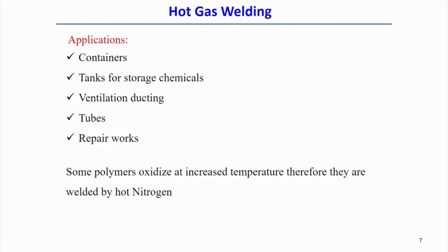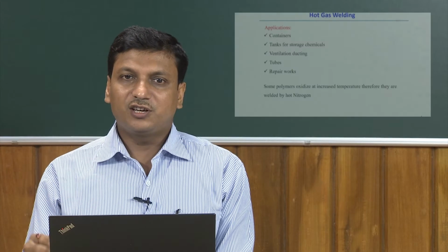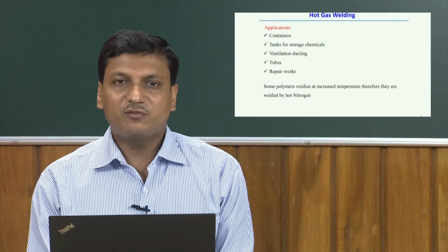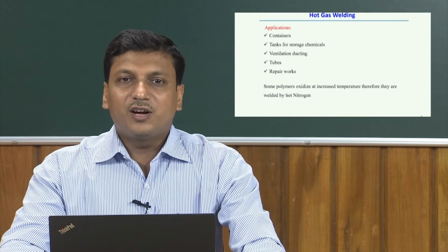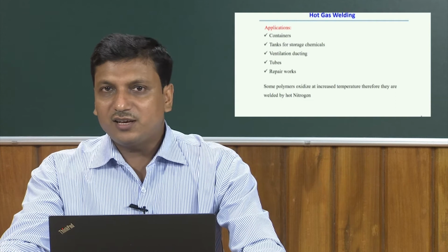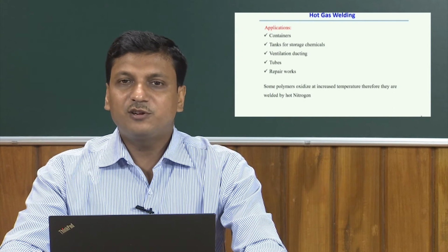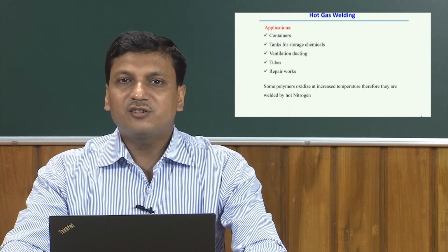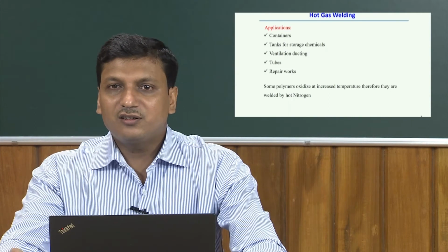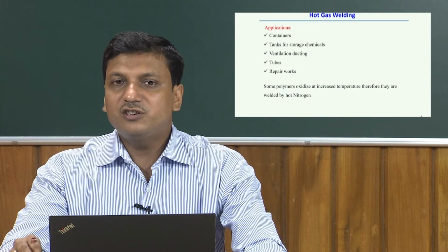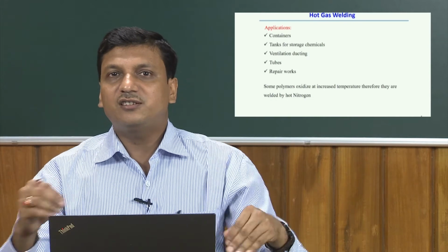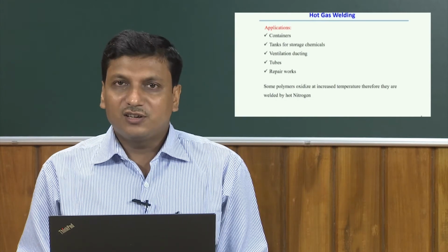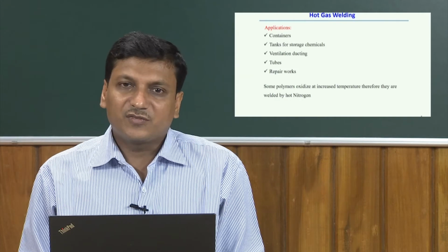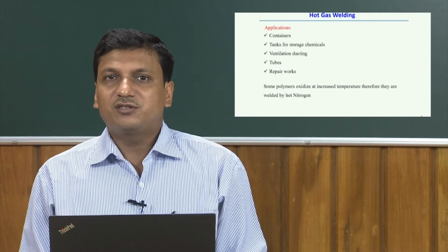We can find repair works, different types of repair works. We can very easily use the hot gas stream for joining plastic components. But one important point is that if the polymeric material has a tendency to oxidize at very high temperature, then instead of hot air we can use a stream of hot nitrogen, because nitrogen protects the plastic polymeric materials from oxidation.